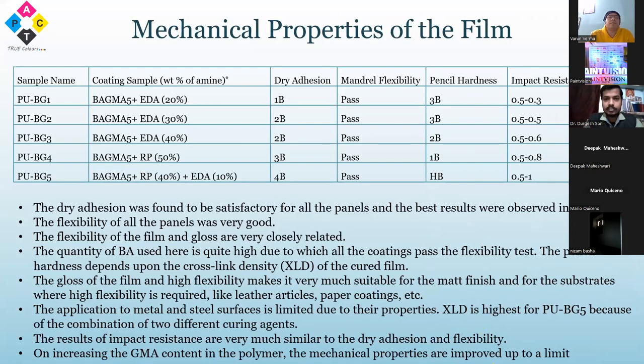Some properties were studied after reaction with ethylene diamine and reactive polyamide. And again, the same pattern was obtained as the previous one. In the reactive polyamide, the results were good. And in the last trial, with the reactive polyamide and ethylene diamine, a combination of both of these was used, which shows some good results. So moving to the next slide.